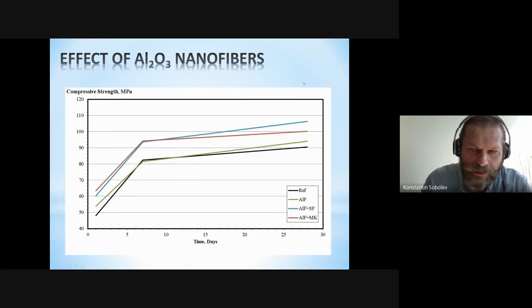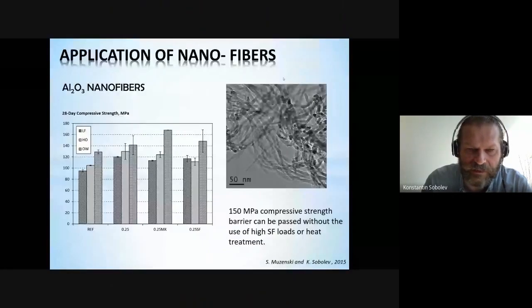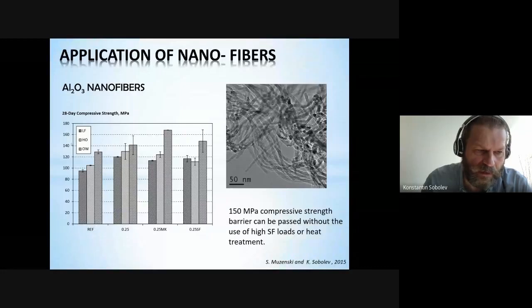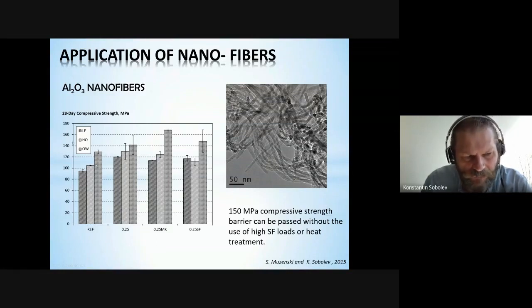And normally, for ultra high performance concrete, compressive strength of 145 megapascal can be relatively easily achieved by different Portland cement systems with silica fume. Going over 150 is kind of the barrier, which would require careful selection of superplasticizer and the type of cement. So this is becoming a challenge, which we overcame with simply the addition of nanoalumina fibers, and also, for example, use of metakaolin and silica fume.